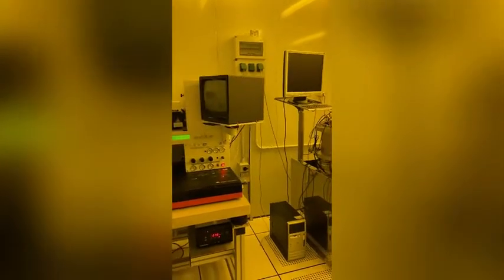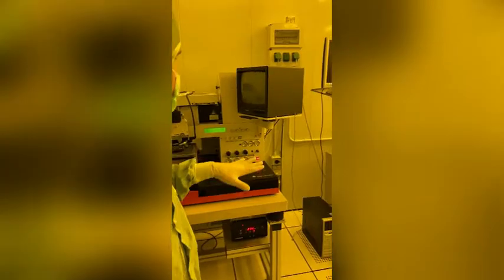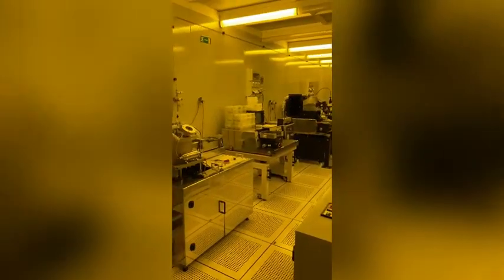So we have a spinner for photoresist, thermal treatment for the photoresist polymerization, and two mask aligners to make the photo masking. With our photoresist, we can reach a pitch of less than one micrometer.